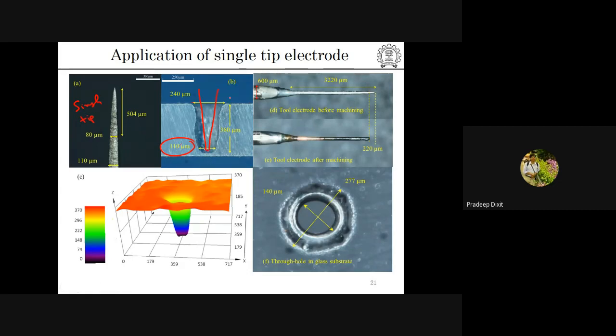You have to remember that the tool electrode is basically bare. As the tool goes down, because of the discharge happening from the side walls, there's always this kind of tapering. So in order to find out the effect of the reduced size, we have to look at the bottom diameter. The bottom diameter is 110. So fundamentally we can use the electrochemical machining process to reduce the size, and those reduced sizes can be used for making smaller glass via.